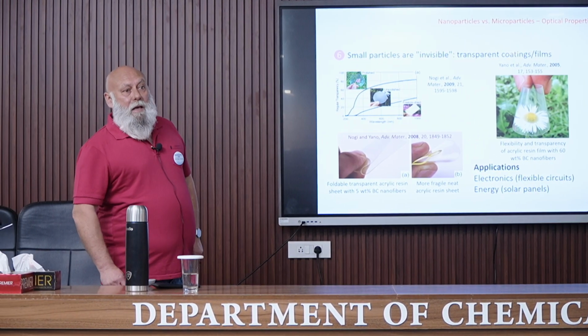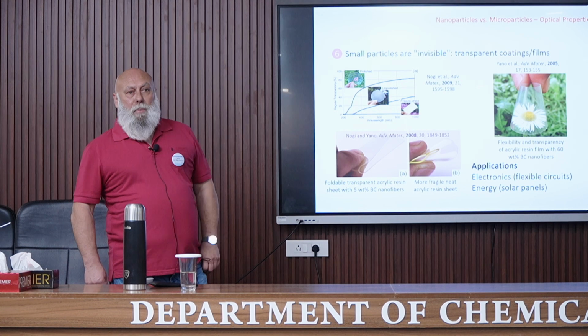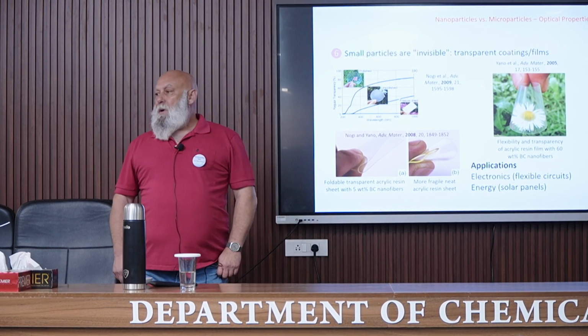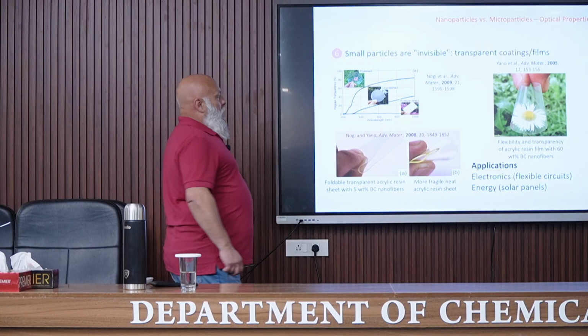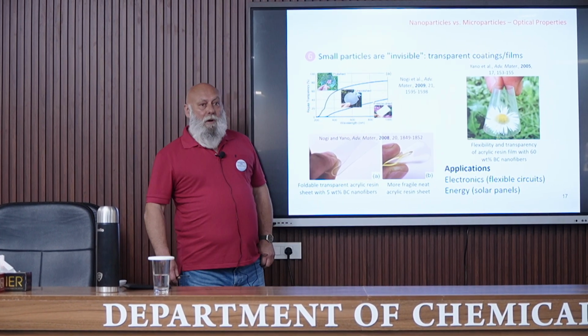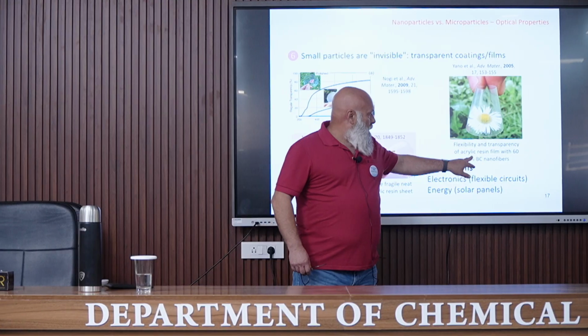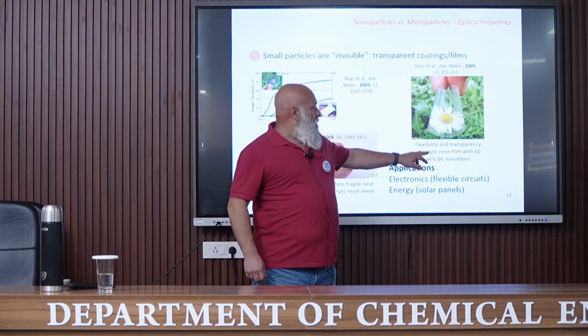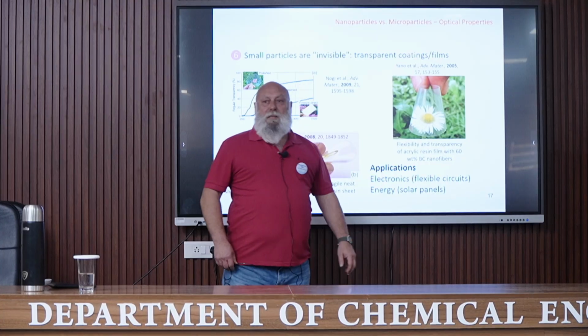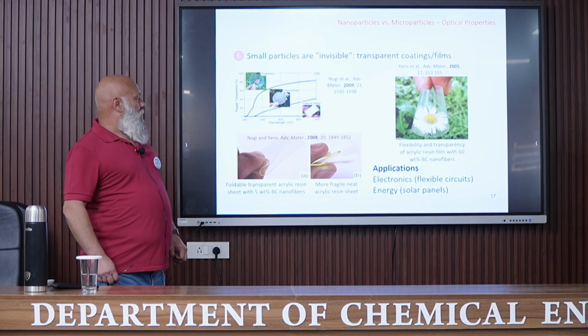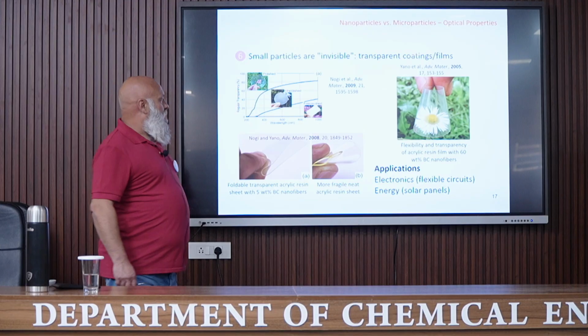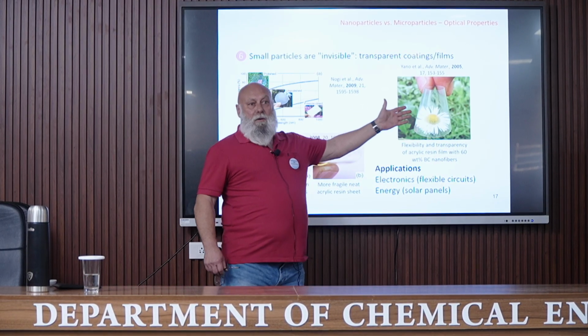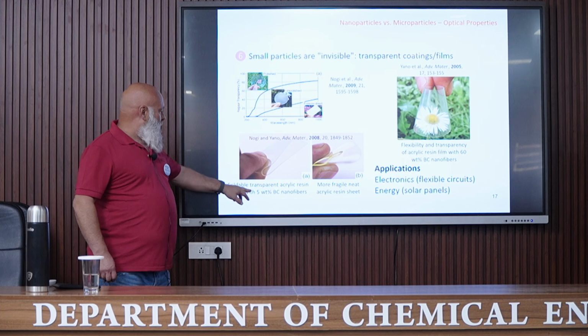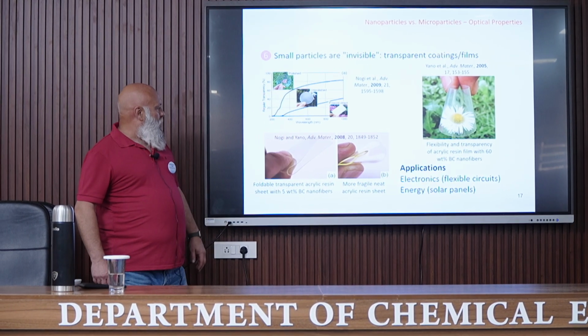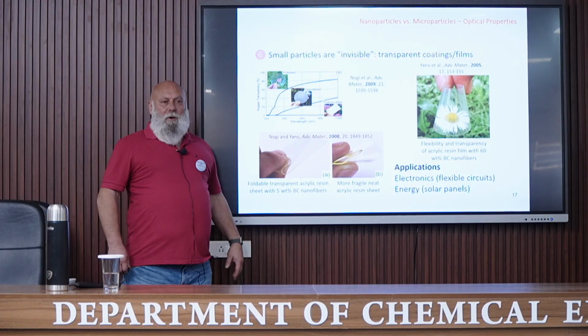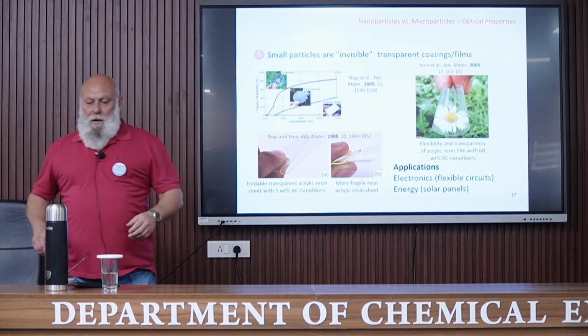Also, this nanoparticle can be mixed with a transparent polymer as matrix. Transparent polymer means amorphous polymer. And we can keep the transparency of the material. You have one example here in which an acrylic resin was used. It was mixed with 60% cellulose nanofiber. In this case, it was bacterial cellulose nanofibers. And you can see that the material retains the transparency. Same thing here with 5% bacterial cellulose nanofibers. The material is still transparent, but the mechanical properties are improved.